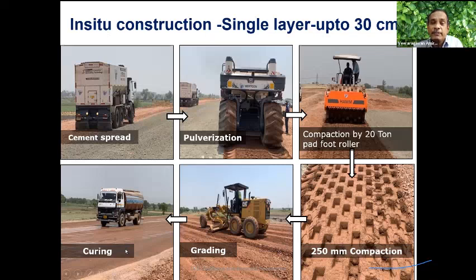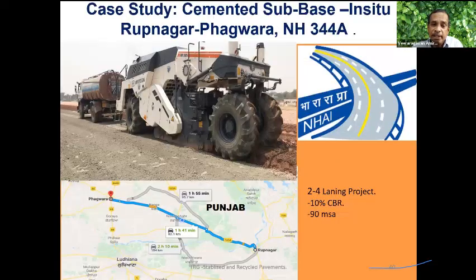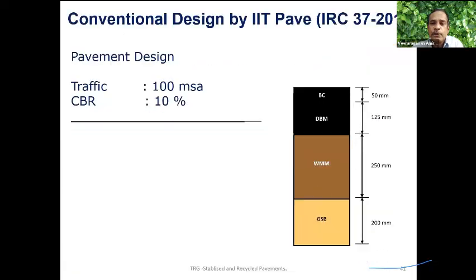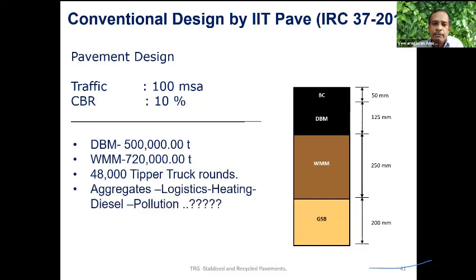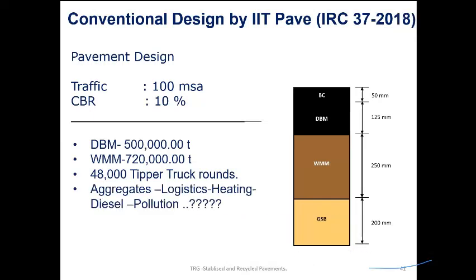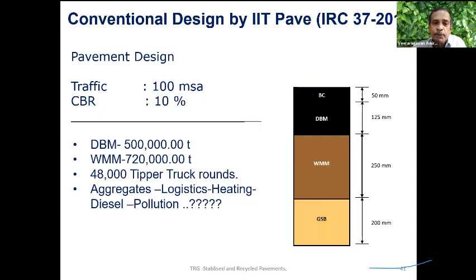You can reduce the thickness from 250 millimeter to 150 millimeter. You can now work out the savings in aggregate. It will definitely result in improved performance as well. This is for a project in NH 344A for a 10% CBR and 90 million standard axles. They worked out what the cost, the pavement layers. They found that so having a dense bituminous macadam of 5 lakh tons, we can bring down, and a wet mix macadam of 7.2 lakh tons.